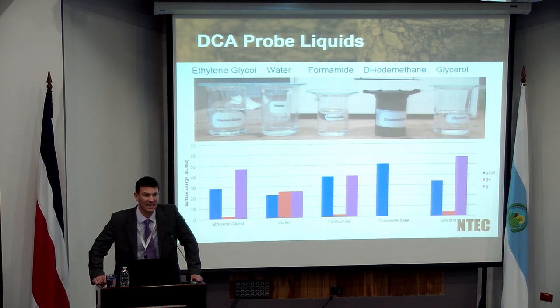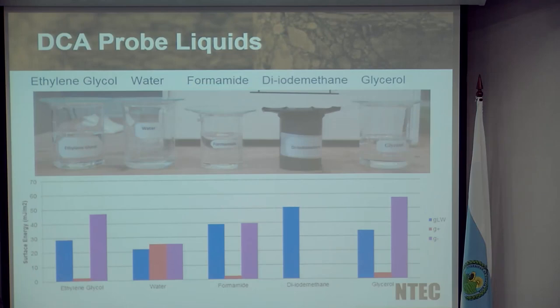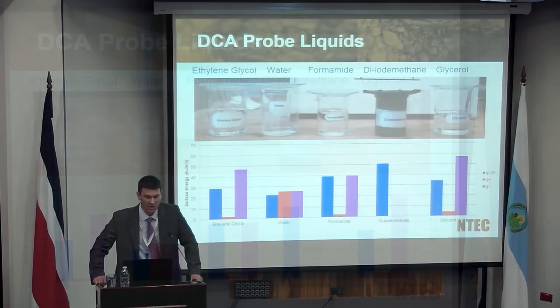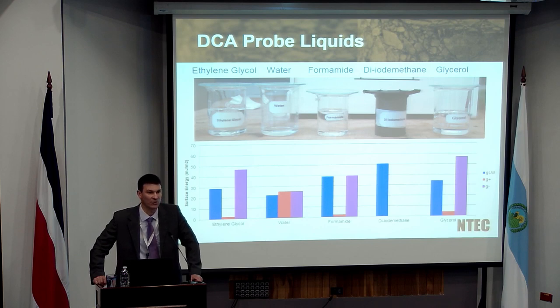I think I mentioned earlier on that you need at least three because you're trying to work out three variables. You've got effectively your surface energy divided into three components, non-polar, an acid, and a base component, so we need to look at least at three probe liquids. We look at five because it allows us to get a much better and more accurate final result. Again, it's worth mentioning, you always need to have a non-polar material because otherwise you can't determine that one parameter. So if we were looking at probe liquids, we would use something called diiodomethane, which is a non-polar liquid. And then we'd have to have a range of different polar materials. So water, for example, is a good example, and various other types, glycerol, ethylene glycol, etc.